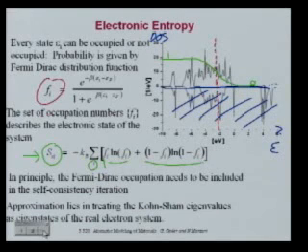It's just that in reasonable materials, metals and semiconductors, they look very much like one-electron eigenstates, and this stuff works. Where it breaks down is typically in materials with very high degrees of correlation, transition metal oxides, where these things don't look at all like one-electron eigenstates. Because what happens in those is, as soon as you do an electron excitation, the whole underlying eigenvalue spectrum changes. Okay? And remember, then it's not an eigenstate. An eigenstate is supposed to be orthogonal to the rest. So if filling or unfilling it changes the occupation of all the other ones and the wave function of all the other ones, it wasn't an eigenstate. Okay? So there, this stuff fails.